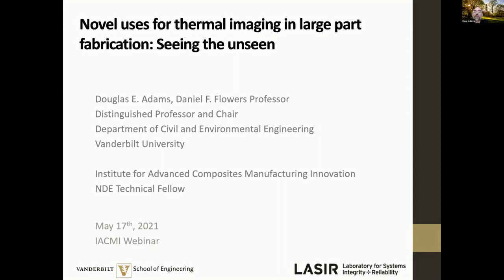Yeah, that's a great question. We have not compared it with CT, but we did with ultrasonic inspection. We're certainly able to see the correlation in terms of location and generally the size of flaws. Another thing to point out is that with something like ultrasound or CT scan, typically you're looking for voids in the material, that high contrast area. If you have a void, you're able to see the presence of that flaw.